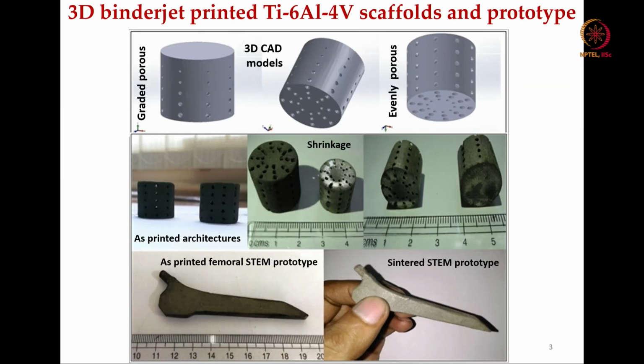So, simple CAD models were constructed, one with gradient porosity and one with uniform porosity. Evenly porous means uniform porosity, and the other is gradient porosity. And then when these CAD models were exported to the 3D printer, we printed it, and subsequently we sintered it, and we found out the as printed architecture, and what is the shrinkage that took place from as printed to post processed cylindrical constructs.